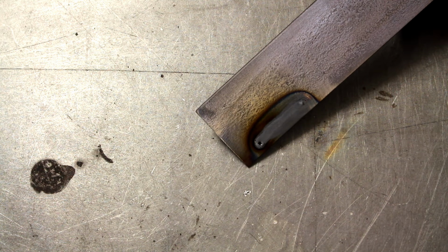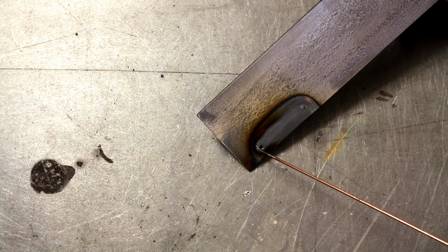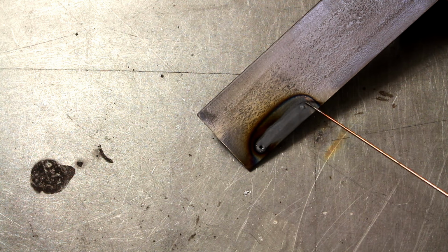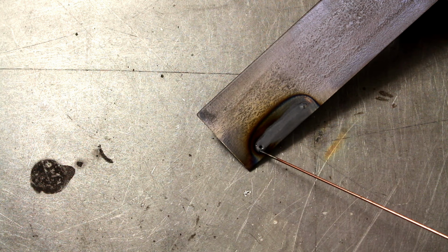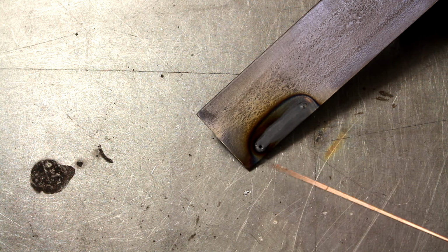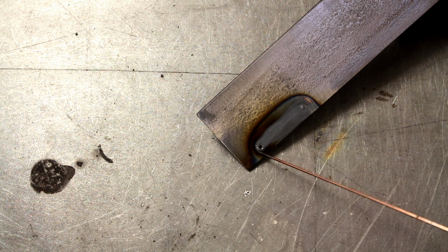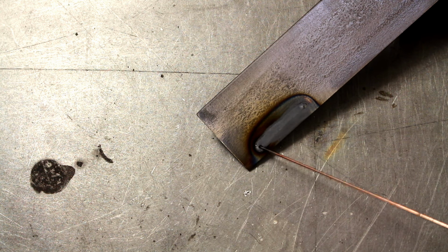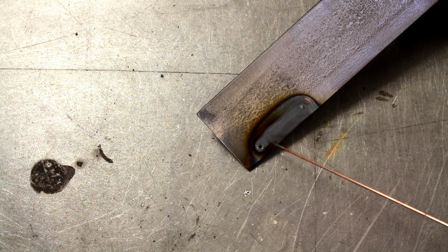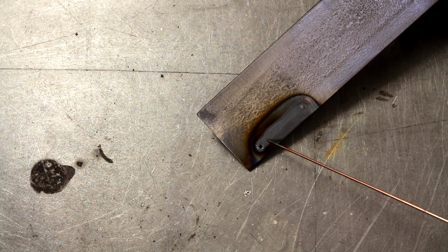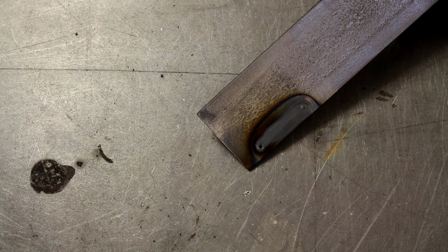All right, so what we did was we melted the steel and ran along in a straight line. Now you did see that nasty little burst at the start. It was probably some mill scale or something still on the steel, which caused that little fart and a bit of a dag there. So this is not steel I'd be using on a motorcycle, but for the exercise it's fine. So now we're going to go back, repeat this exercise, and we're going to start to slowly add some filler rod into this to build up a weld.